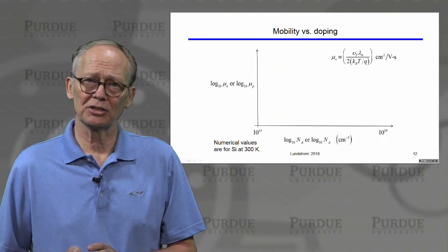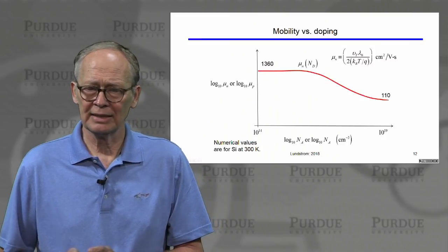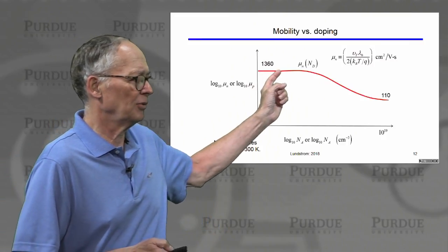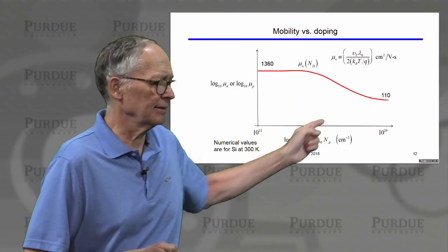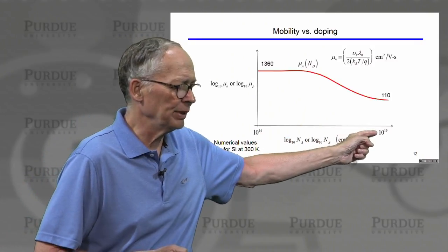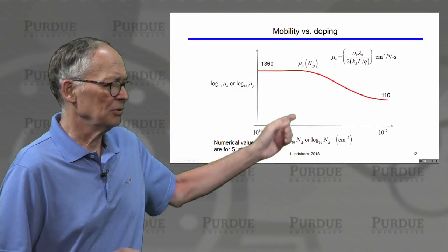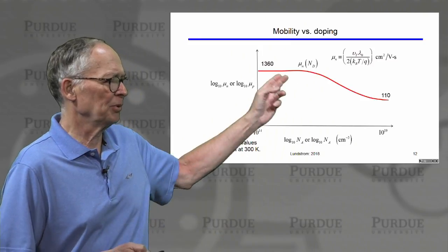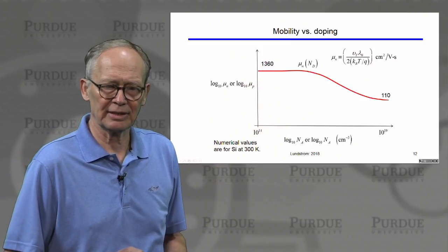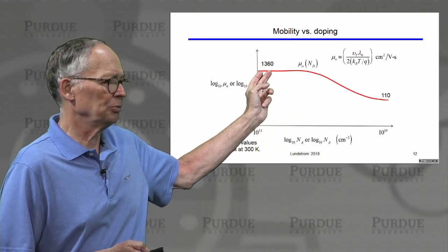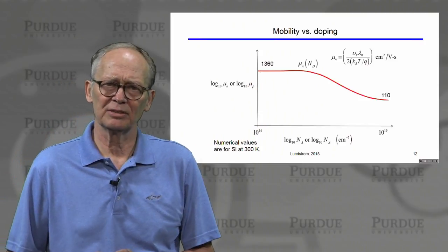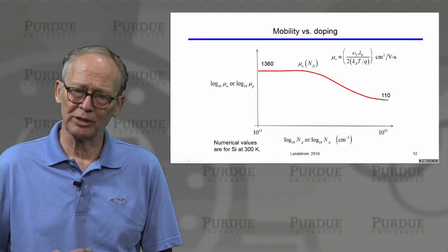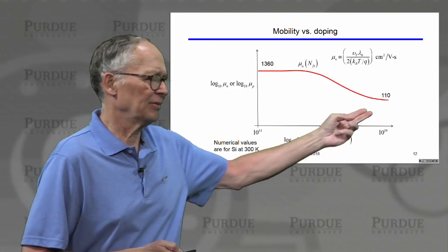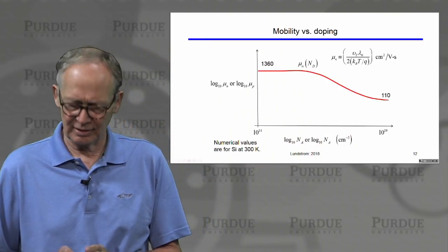If I were to measure the mobility as a function of doping in a semiconductor, I might see the mobility for electrons in silicon, as a function of the doping of the n-type silicon, do something like this. The numbers here are typical values for silicon. If it's lightly doped or pure silicon, the mobility is over 1300 centimeters squared per volt second. If it's heavily doped, the mobility is significantly lower.